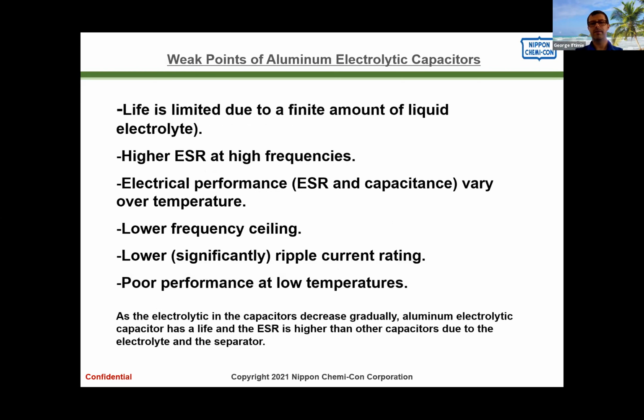Weak points of aluminum electrolytics. Of course, you have a finite amount of liquid electrolyte. You will consume that as a part goes through its life, and you're going to have a limited life because of that. Because you have a liquid electrolyte, you tend to have a higher ESR at high frequency, and you tend to have a higher ESR at low temperature.